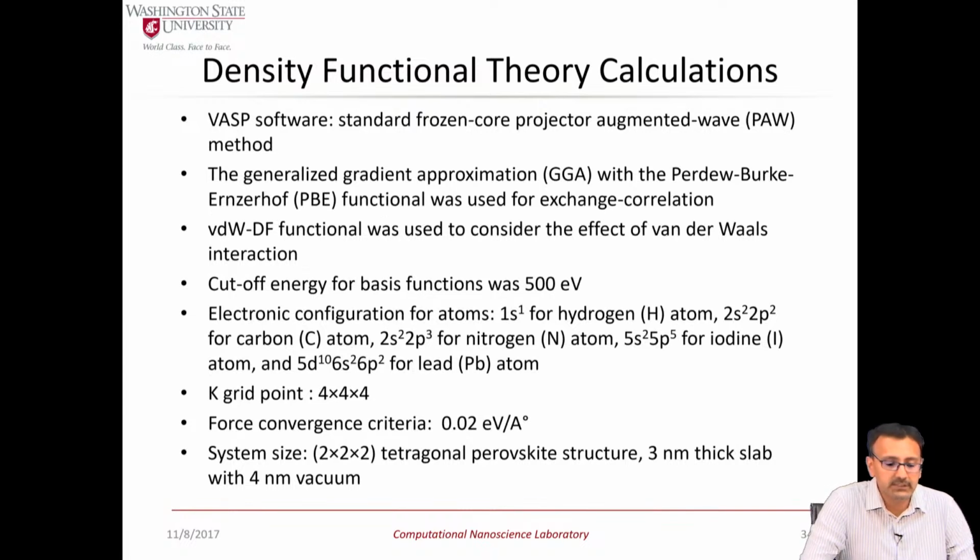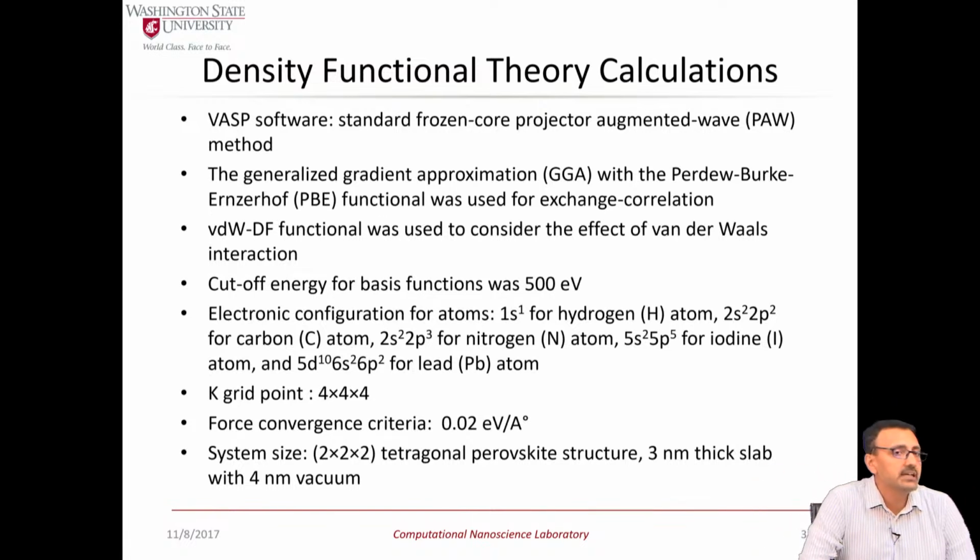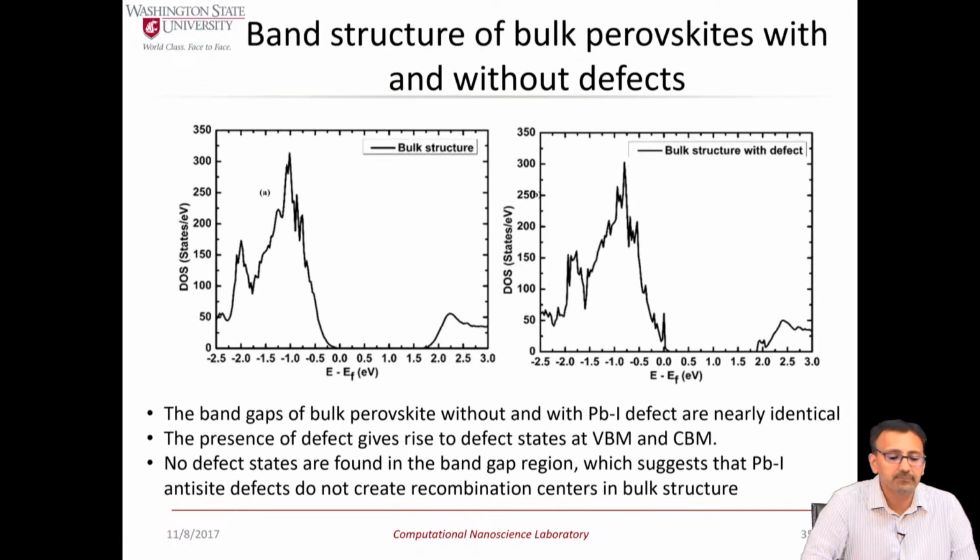The other aspect that we did a sensitivity analysis on is, if you introduce an atomistic defect, the xy direction, the planar dimension of the film, has to be large enough that you don't have any spurious defect interactions, because what we really wanted to model is dilute defect concentrations. So we did a sensitivity study to choose the appropriate system size, which is always very important.